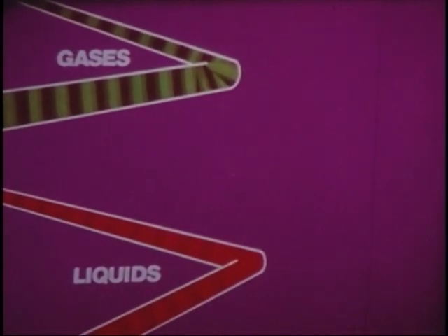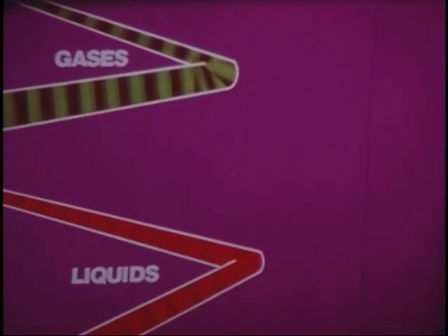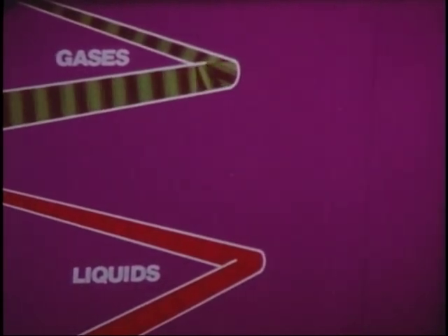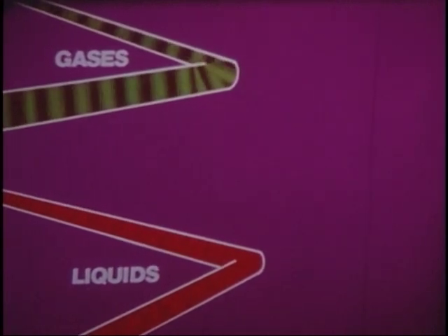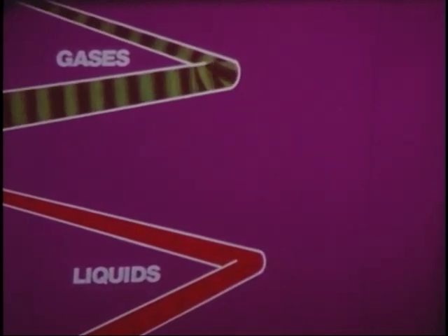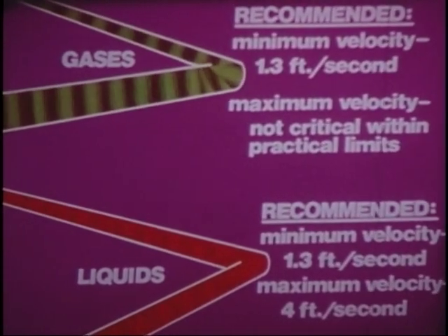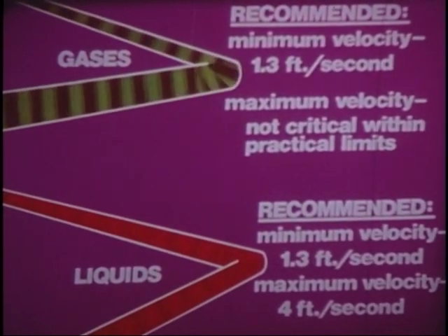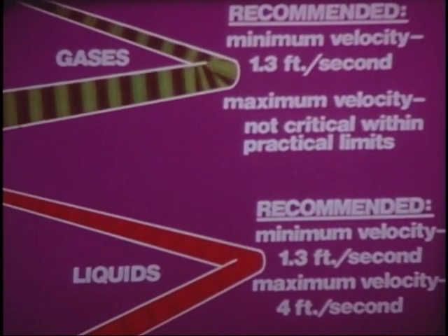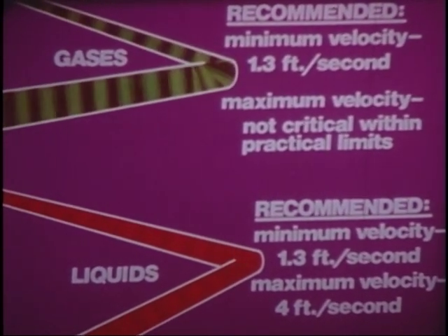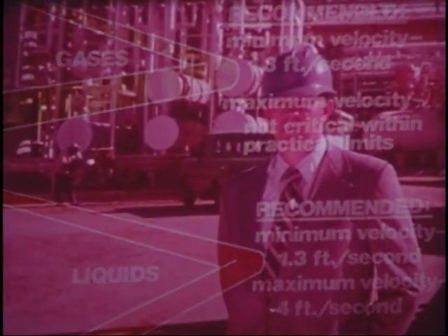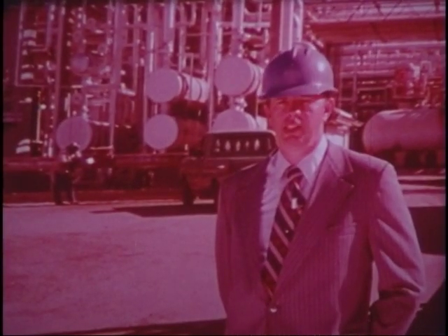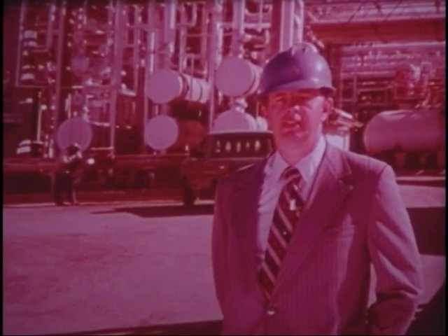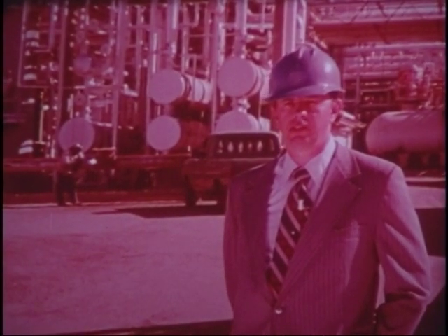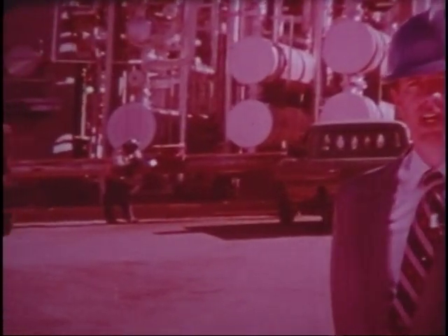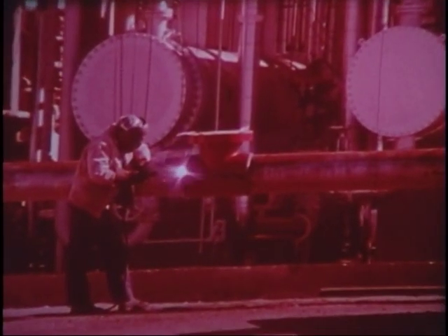No flow conditions can allow the contents of a pipe to reach higher temperature than with flow conditions. While flow conditions help to dissipate heat, they also speed up the quench rate, a factor in cracking problems. Follow these recommendations when dealing with unstable pipe content. Our process plants with essential piping systems can benefit from the technology and skills that others have long since found to save time and money.